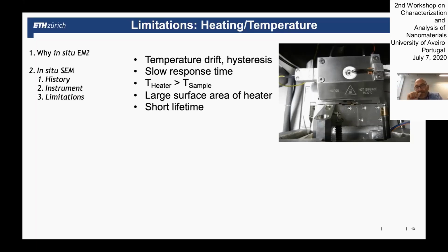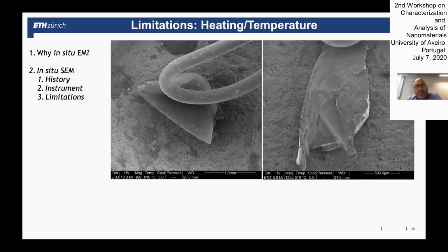That's one of the issues that is not trivial to overcome. And especially when you have nasty gases in your chamber, the heater can easily corrode and get damaged. Then another thing is when you heat something, you're often also interested in the temperature. Now, how do you measure the temperature for powder very precisely?